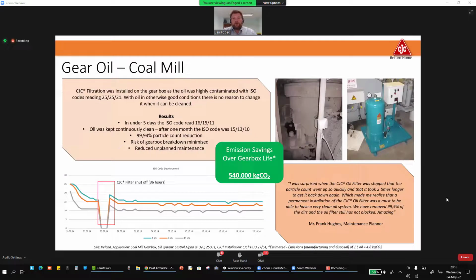To give you another example, we had a coal mill gearbox with very contaminated oil, a lot of coal in it, and we put on an online particle counter, so you can see the cleaning level of the system online. In 5 days, the ISO code, the cleaning level of the oil, was reduced from 25/25/21 down to 16/15/11. This alone will give you emission savings on this gearbox of 540,000, which of course is what there's focus on today.